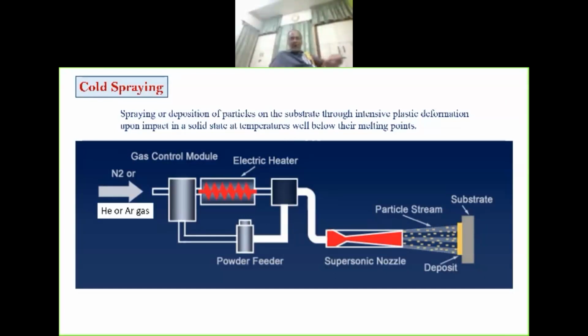One of the new kids in town. What do we do here? We feed helium, argon, or nitrogen gas at a very high pressure. How much? 50 bars, 60 bars, 40 bars. Normally not below 40 bars. Okay? We heat it to a gentle temperature. For example, you are spraying aluminium, melting point is 660. Don't heat it beyond 300. You have a powder feeder,